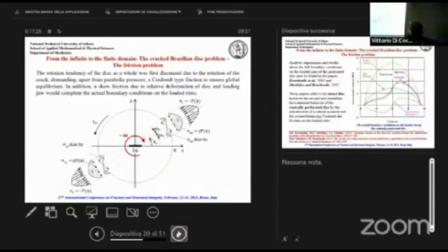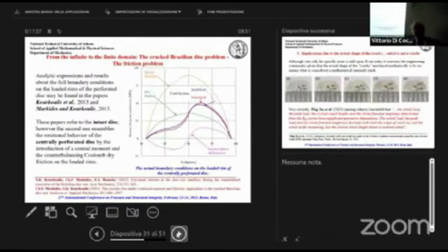What is left now is something that is usually ignored. If we have a disk with a crack, which is loaded neither parallel nor normal to the crack, the equilibrium conditions cannot be satisfied unless we accept a distribution of friction forces. It is not possible for the disk to be in equilibrium with a crack loaded neither normally nor parallel. This problem, in fact, what is the necessary distribution of friction forces on the disk below the contact arc, couldn't be solved until Dr.